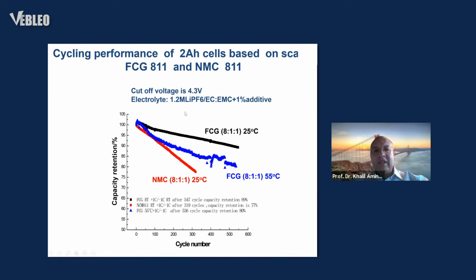So these are the initial data at 4.3 volt with the additive. You can see that this is actually not so bad as a result for NMC under development that the industry is trying to enable. It gives us almost 80% retention after 300 cycles. However, the FCG shows far much better results, with almost 550 cycles with 10% fade only. Even at high temperature, the FCG outperforms the NMC 811 at room temperature.